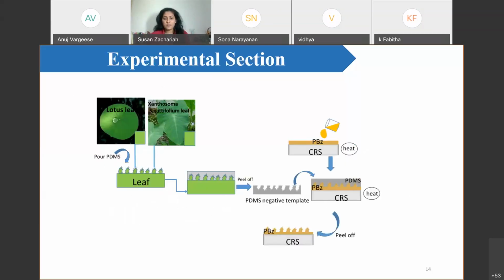This is the flowchart which I have used in my research. I have used two kinds of leaves: one is lotus leaf and the other one is Xanthosoma sagittifolium leaf. On each leaf, I have poured the PDMS solution. It is heated at 60 degrees Celsius for 24 hours, so it gets solidified on the surface of the leaf.